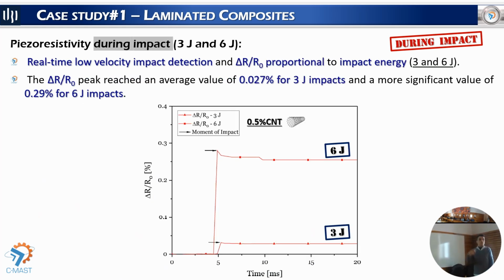We went even further and we monitored the electrical signal during the impact tests for both 3 joule and 6 joule impacts. And here in this graph we have the electrical resistance variation as a function of time during the impact tests. At the beginning, the resistance of the materials was very low compared to the values reached after the impact. So here we can see that immediately after the impact we have a significant increase in the electrical resistance of the materials. So the system was able to detect the impact occurrence. But even more, by estimating the variation of the electrical resistance, we can have an idea about the energy that was involved in the impact.